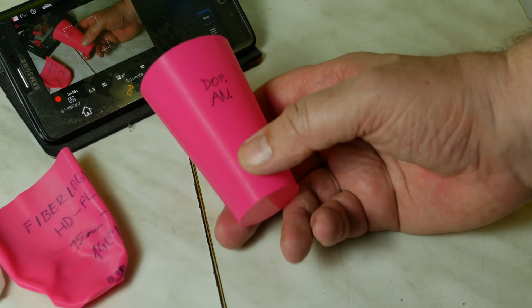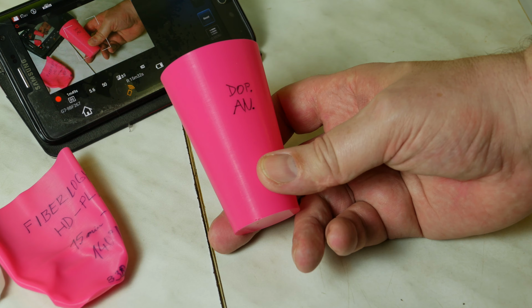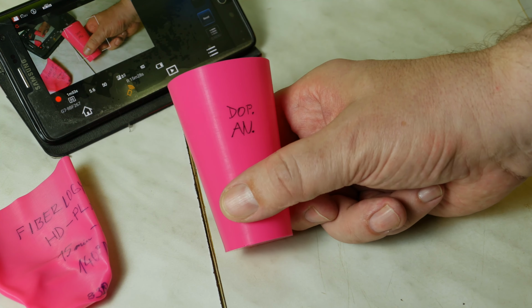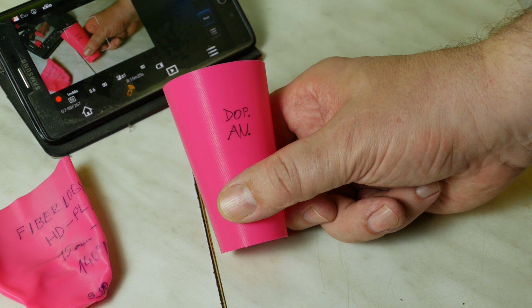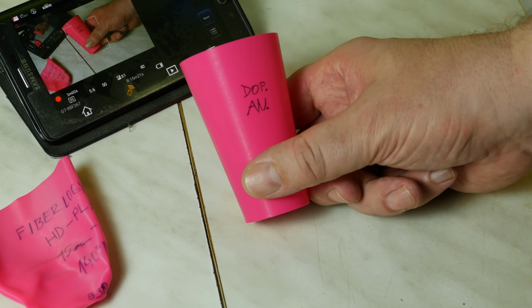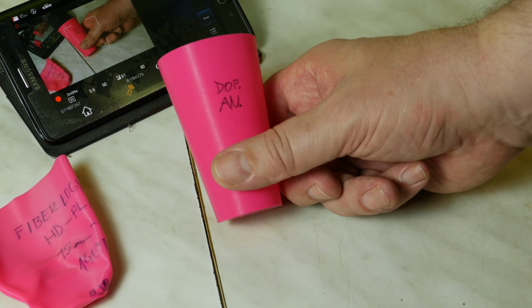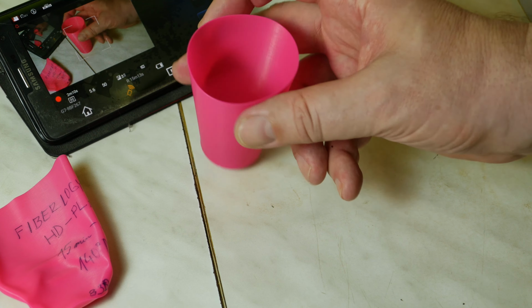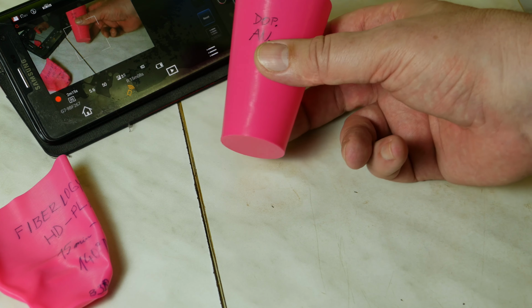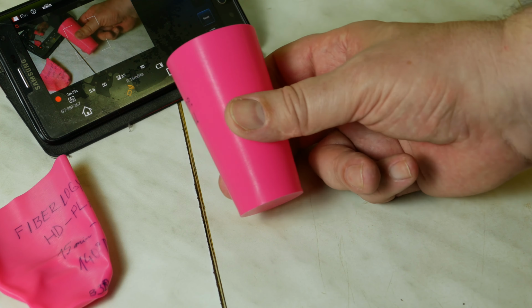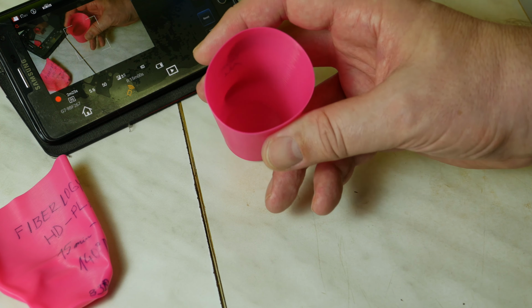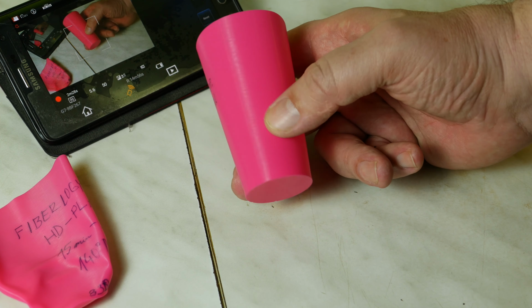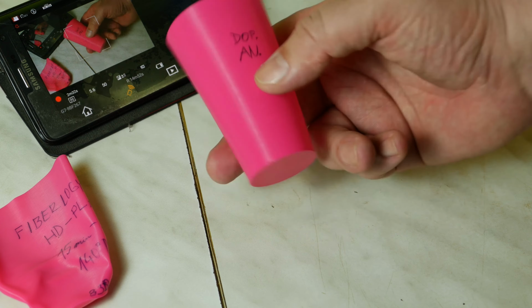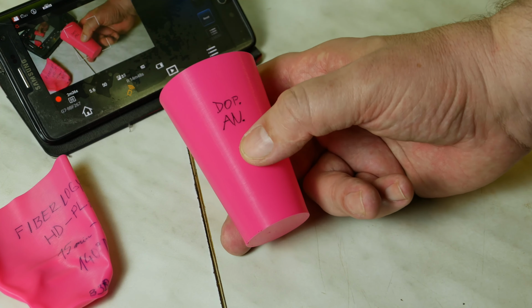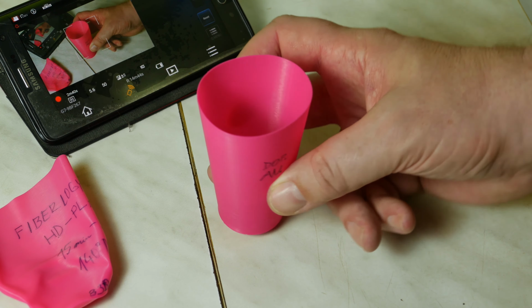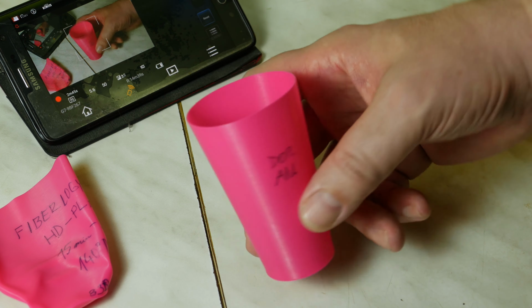Number 3, bronze medal. HD-PLA with annealing process. Why number 3? Why not a better place? Because this material, the manufacturer says, is 140 temperature resistance, but you can see how soft it was. Okay, the shape of this can is the same as it was, but on the top side you can see this is deformed and it was really soft. And if you think about the really difficult procedure of the annealing process, you must think about your parts. What about stretch of parts, etc?